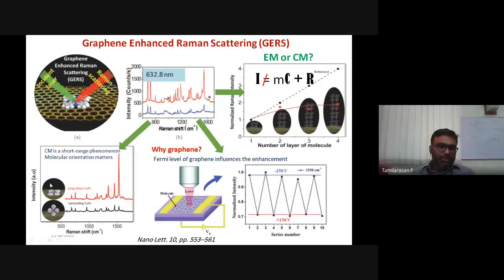Similarly, they have taken a single molecule, and when the molecule is oriented differently, it gives a different Raman signal. When it is vertically aligned, that means the charge transfer site is not in contact with graphene, and you are getting a poor signal. When it is in contact, you are getting a strong signal. That means if the charge transfer site is in contact with graphene, there is a possibility of charge transfer, and because of that, you will get chemical enhancement.